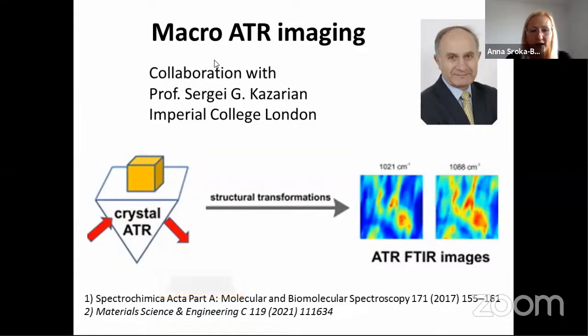So we used macro ATR imaging to analyze our biomaterials. On the ATR crystal, we put our biomaterial, and the crystal was attached to the FPA detector. So the imaging was done on the whole surface, which was in contact with the crystal. Maybe I will shortly explain the imaging system: it is not a single spectrum, but several spectra connected in the XY directions, and those groups of spectra we connect into images.